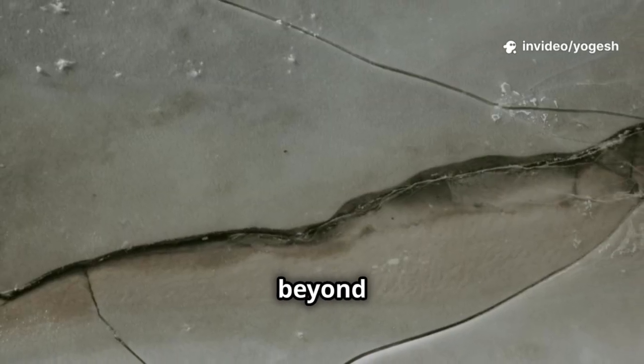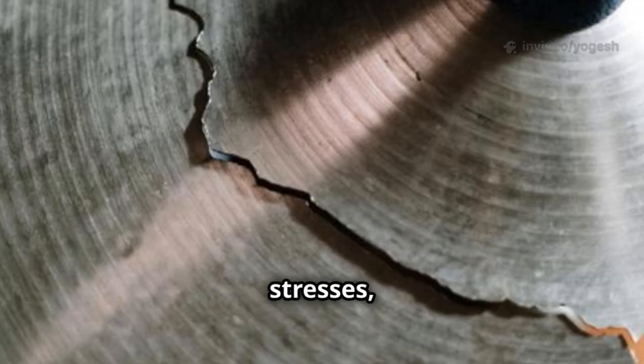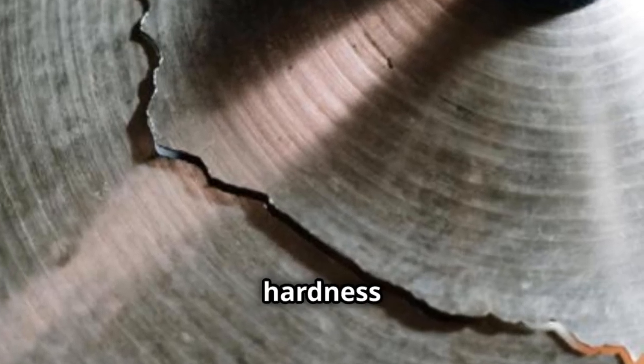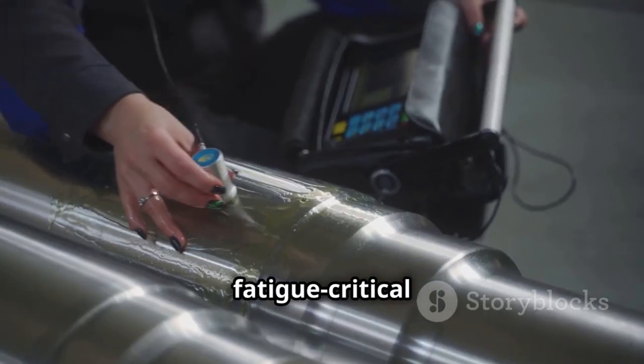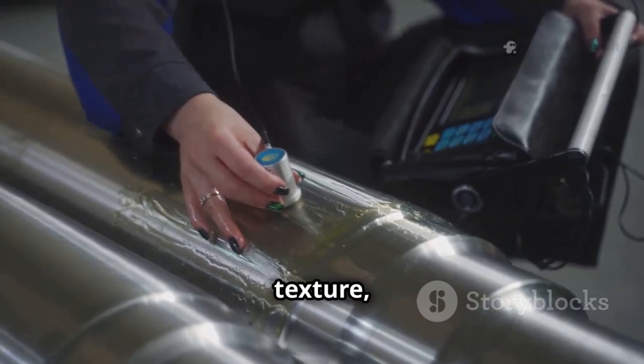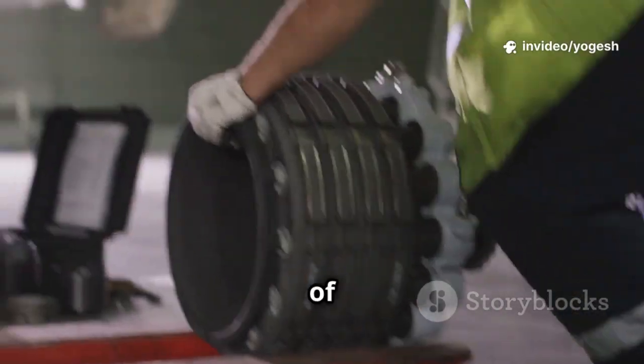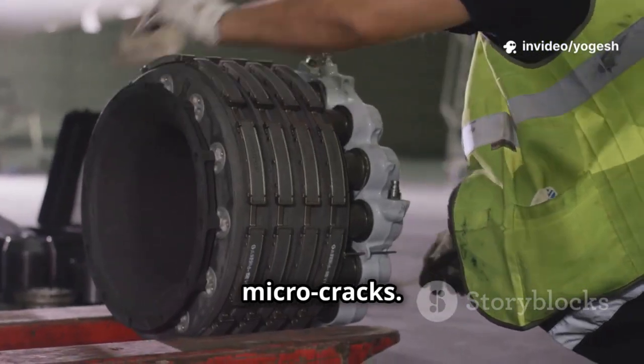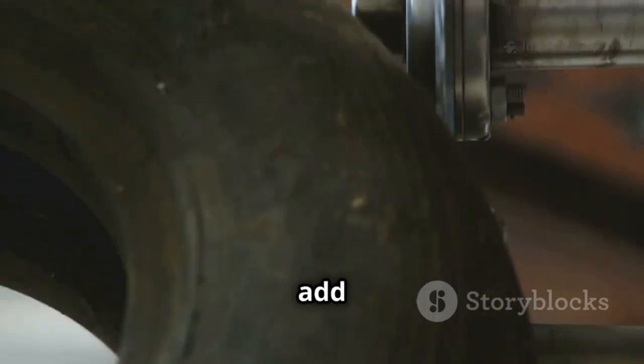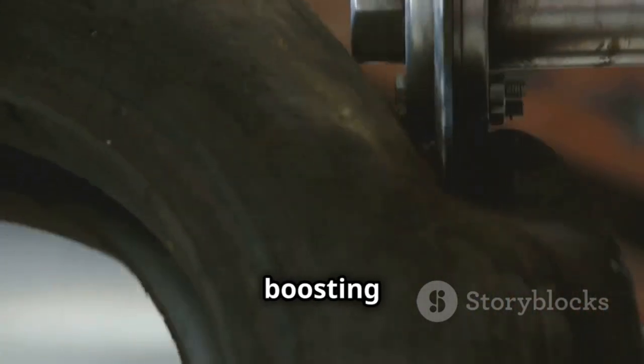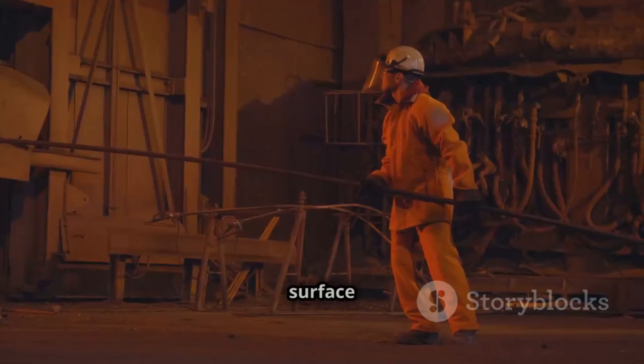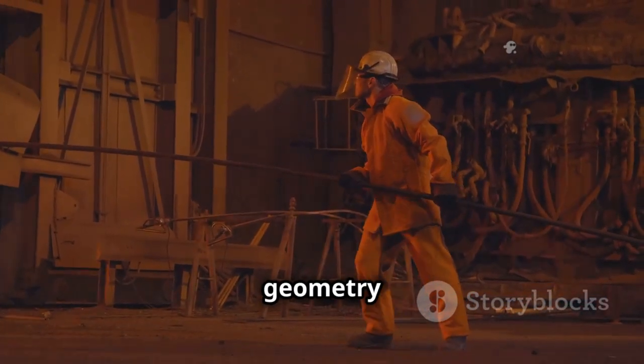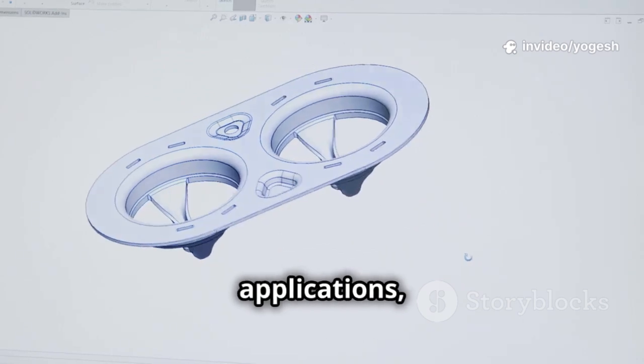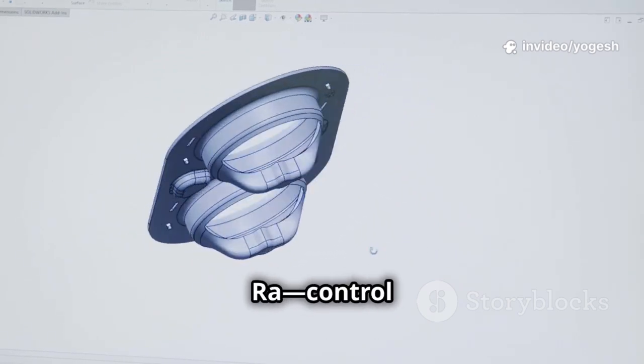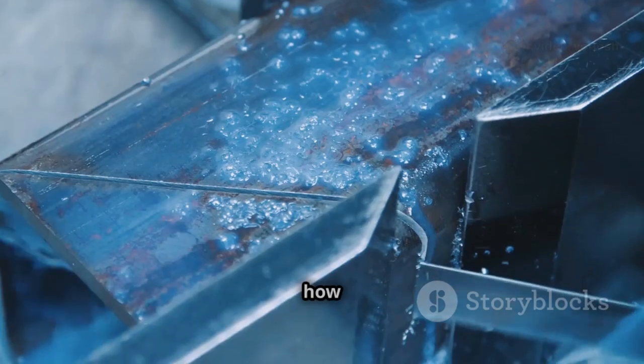Surface integrity goes beyond texture. Manufacturing can introduce stresses, micro cracks, or hardness changes. For fatigue-critical parts, specify not just texture, but also process and verification of residual stress or micro cracks. Techniques like shot peening add beneficial compressive stress, boosting fatigue life. True surface engineering considers both geometry and metallurgy. For critical applications, go beyond Ra. Control the whole surface story. That's how you design for durability and safety.